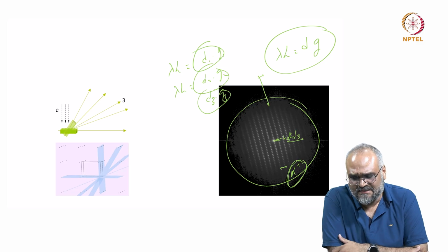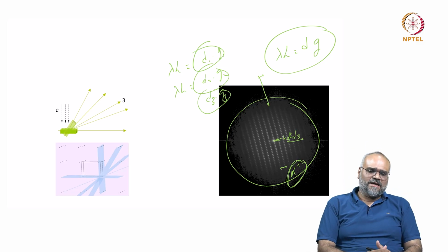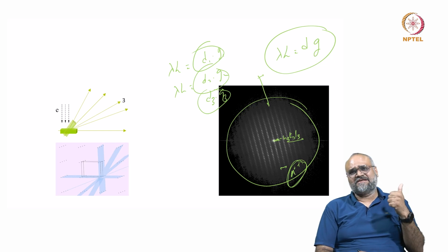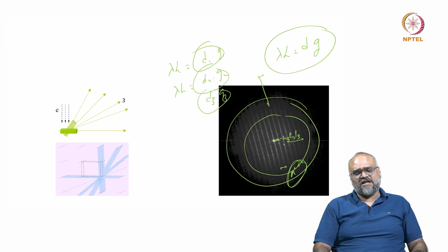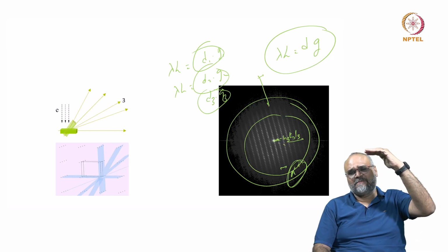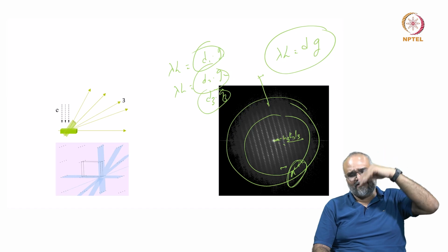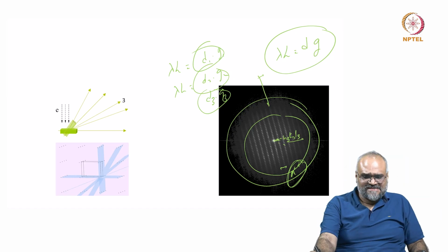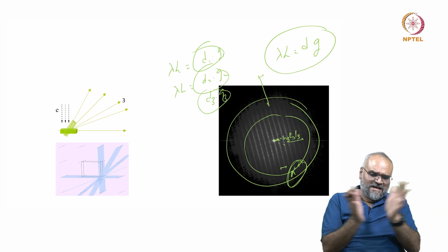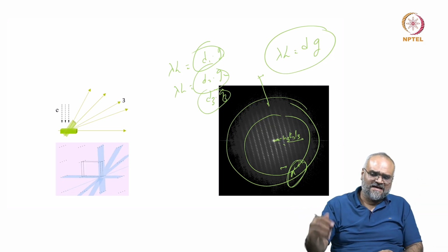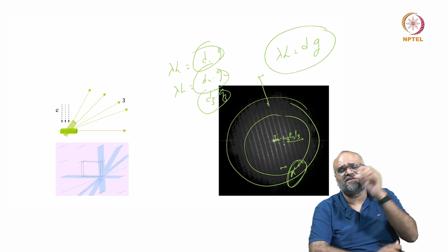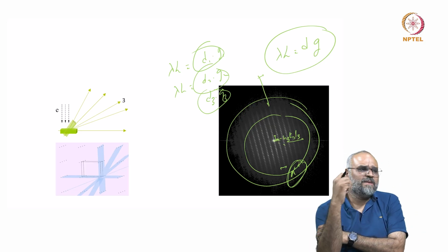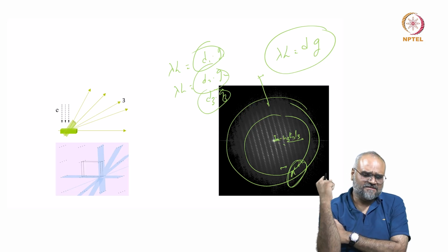indexing diffraction patterns. So, please understand that when I do electron diffraction, I not only look at the projected information of the reciprocal lattice, but these are also projection of information from the backfocal plane from the objective lens, and then I can physically, through the combination of projection lenses, I can change the magnification and increase the distances and accurately measure what my lattice parameters are and make more sense out of the crystal structure.